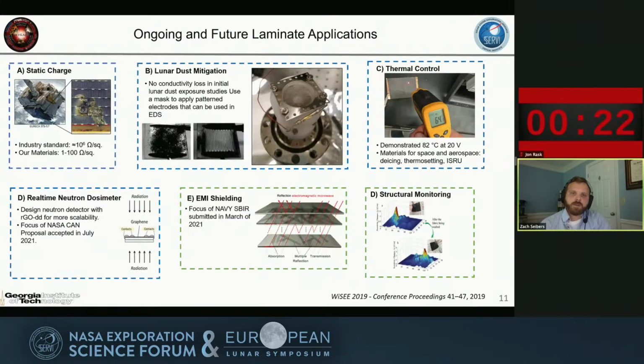And so just to briefly summarize, we started off this venture with thinking about static charging, and we've ended up beating the performance we needed to do this by at least 10 to the 6 ohms per square. And then we're looking at lunar dust mitigation concepts. So right now, these are early stages, but we hope to transition to schemes using more advanced systems like an EDS system that you would conventionally see from NASA. We've talked about joule heaters, and then of course, like I briefly mentioned at the beginning of the talk, the graphene is also being looked at in EMI shielding and real-time dosimetry cases. And then we could also envision these types of things in structural monitoring. So you really have a one layer kind of does a multitude of operations, or at least has the potential to.